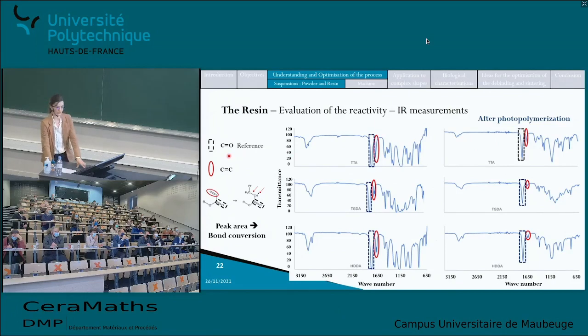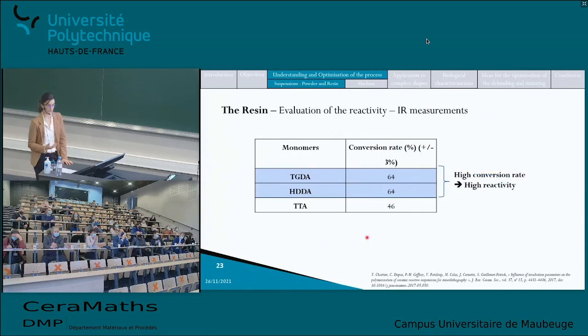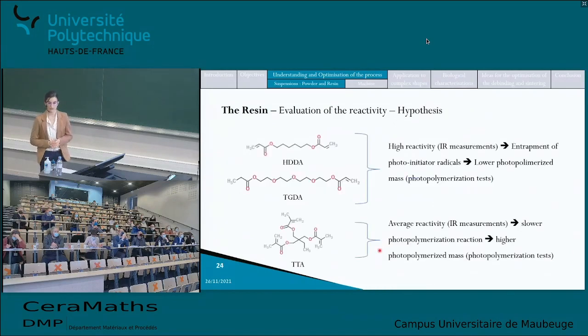And thanks to the calculation I found in an article, I was able to calculate the conversion rate of each of the monomers. And what appears here is that the TGDA and the HDDA are actually the monomers with the highest conversion rate, meaning that they are the monomers with the highest reactivity compared to the TTA. So how can we explain that? Well, a high reactivity can be linked with the entrapment of photoinitiator radicals during the photopolymerization reaction if this reaction happens too quickly. So this can explain the lower photopolymerized mass obtained in the first test, whereas the average reactivity that was shown for the TTA in the IR measurements leads to a slower photopolymerization reaction, which can explain the higher photopolymerized mass in the first test because there was no entrapment of the radicals of the photoinitiator.